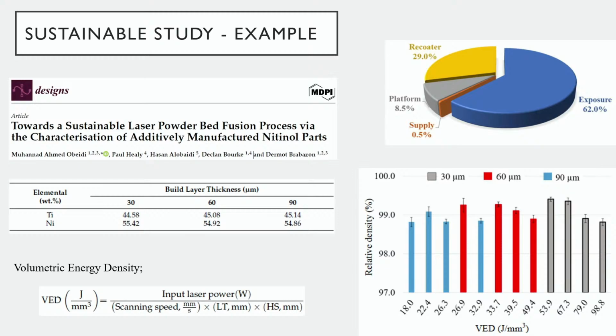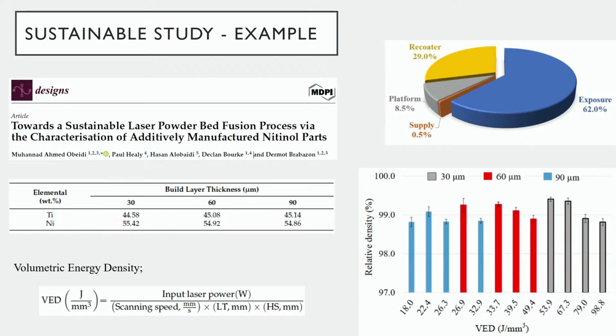So in blue, these are the 90 microns layer thickness with these volumetric energy densities, and then 60 and 30 microns. My aim is to achieve the maximum density. I found, working with this VED, I got this density, which is very close to the 30 microns. Then I took only these samples for further testing: mechanical properties, chemical composition, phase composition, and so on. So this was a promising sample.